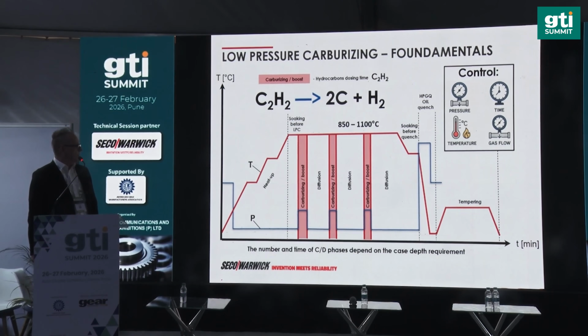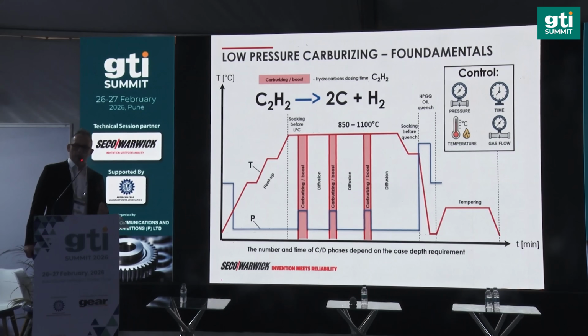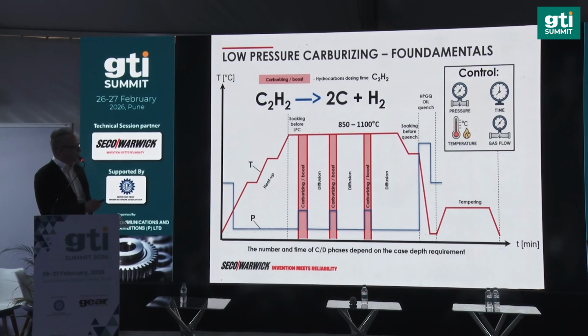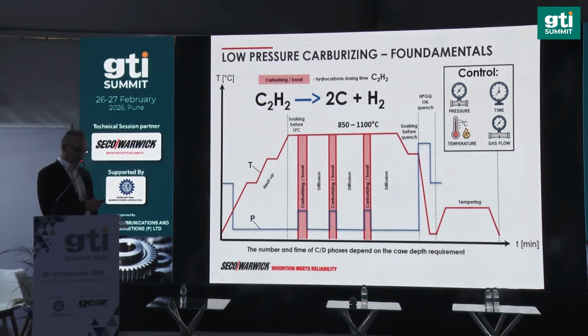How about the temperatures? Due to the nature of vacuum furnaces, they are purposely designed to be able to handle even 1100 Celsius degrees, so there is no issue in running the processes at elevated temperatures like 950 or 980 Celsius degrees, which will bring us a lot of benefits coming from the diffusion law and shortening the process time. What do we control besides the temperature, naturally? We do control pressure, time, and gas flow of the acetylene.